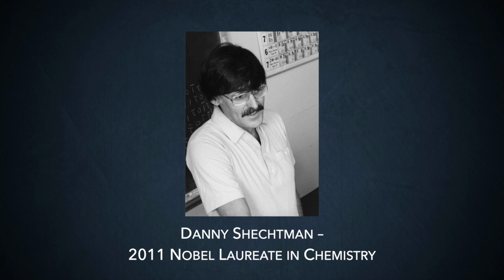And one of the first things we tried melt spinning was for a guest scientist who had come to NBS at that time named Danny Schechtman. He was interested in doing some rapid solidification of aluminum alloys, and one of them was an aluminum manganese alloy. So these are primarily aluminum with small amounts of manganese or other elements added to it to melt spin. And a technician in this laboratory, where I had this melt spinner constructed, then did this for Danny.